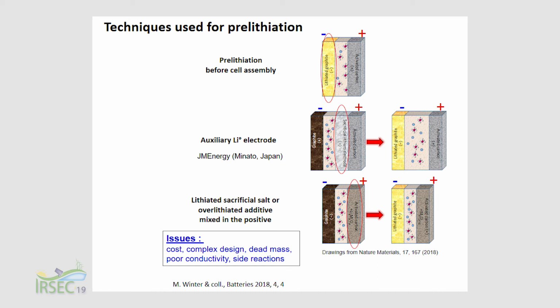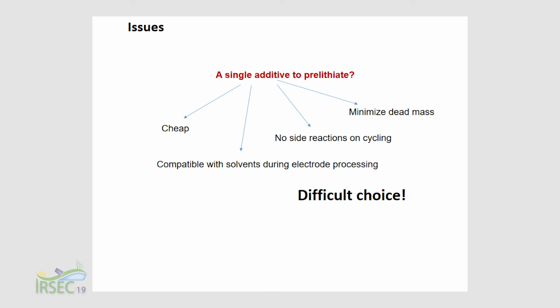But none of these different techniques is satisfactory. There are still some issues such as cost, complex design, dead mass, and poor conductivity of the lithium additive. And side reactions at different levels. And our analysis was the following. It is very difficult to find one single additive for pre-lithiation which gathers all the needed requirements. To summarize, to be cheap, to minimize the dead mass in the positive electrode, and to have no side reaction during the electrode processing, no side reaction on cycling.